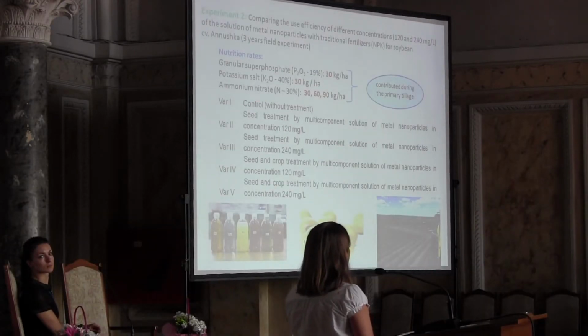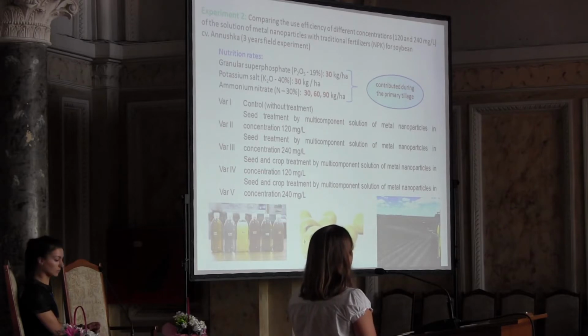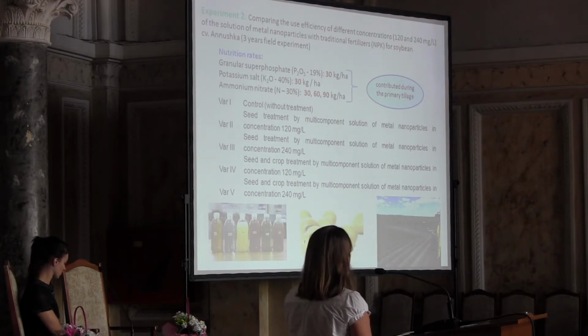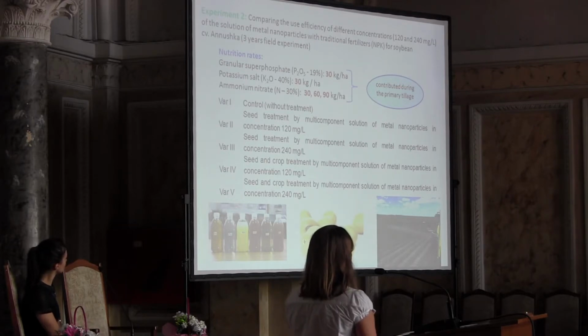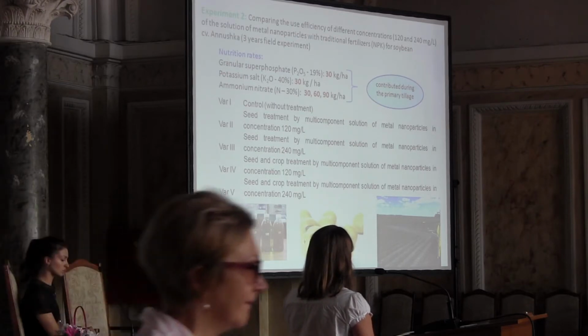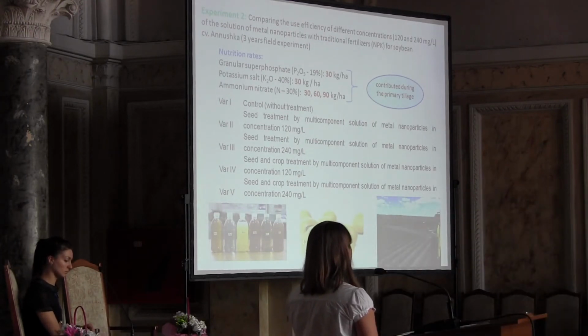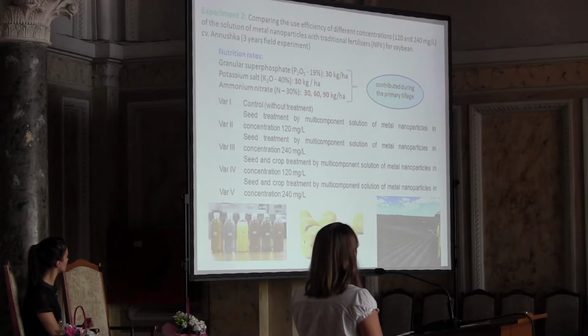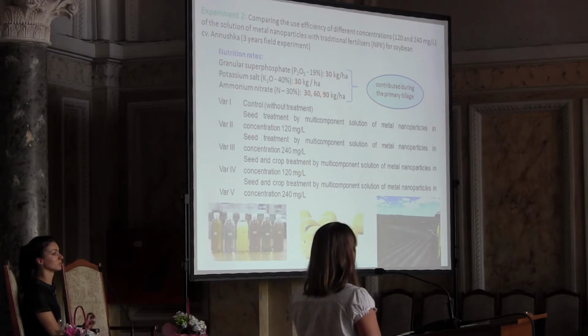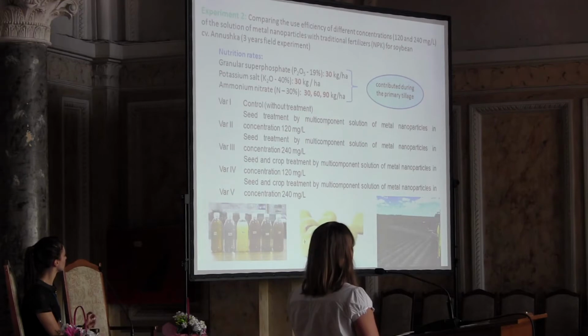The second experiment focused on comparing the use efficiency of different concentrations of the solution of metal nanoparticles with traditional fertilizers for soybean of the ultra-early cultivar Anushka. As in the previous experiment, it was a 3 year field experiment. Different nutritional rates were used: granular superphosphate and potassium salt in doses of 30 kilograms per hectare, and different doses of ammonium nitrate, 30, 60 and 90 kilograms per hectare, were applied during the primary tillage.